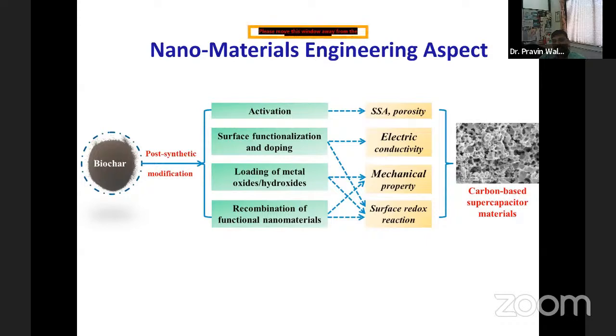So the third important strategy is that you can load metal oxides and hydroxides on that carbon material. By loading those metal oxides or hydroxides, the mechanical strength and rigidity of that electrode material will increase, right? And at the same time, because these metal oxide or hydroxide sites are available for redox activity, surface redox reaction will increase. And this single strategy will definitely help you to increase the mechanical property, so your cyclic stability will increase. And that is a good advantage, because we are looking for highly stable batteries as well, right? And if surface redox reactions increase, it means your energy density will also increase. So this is another important strategy.